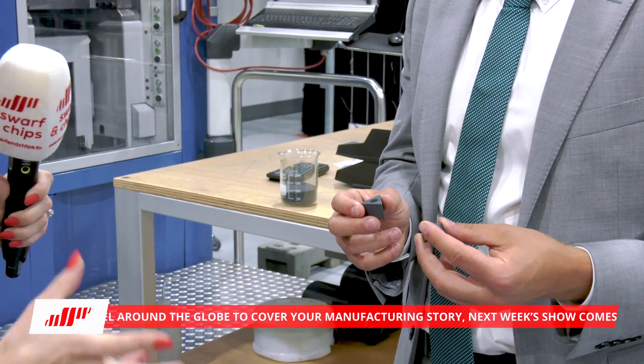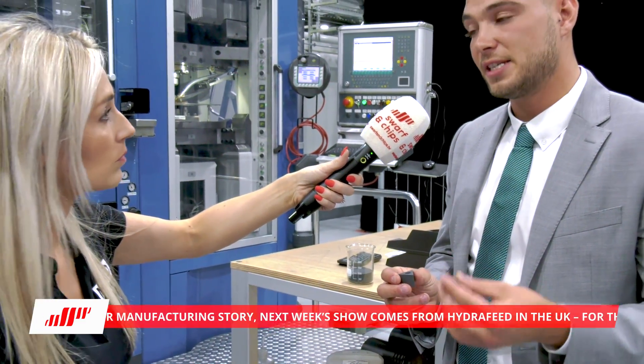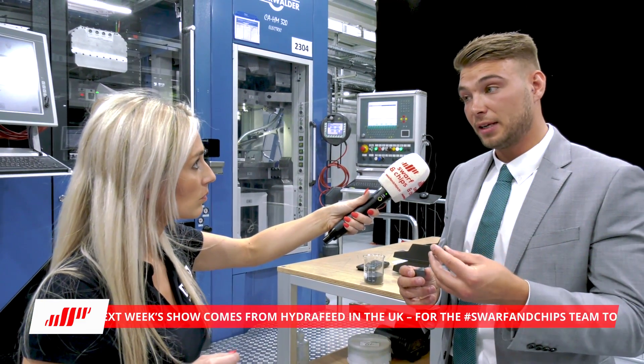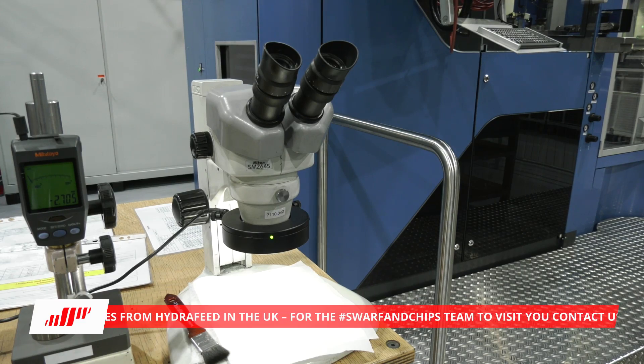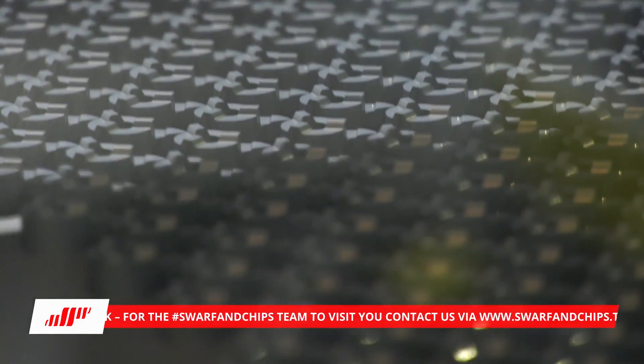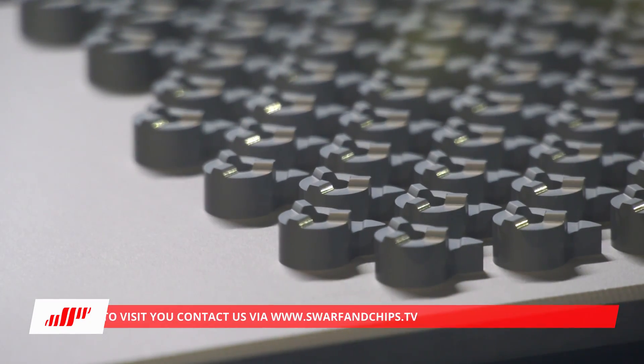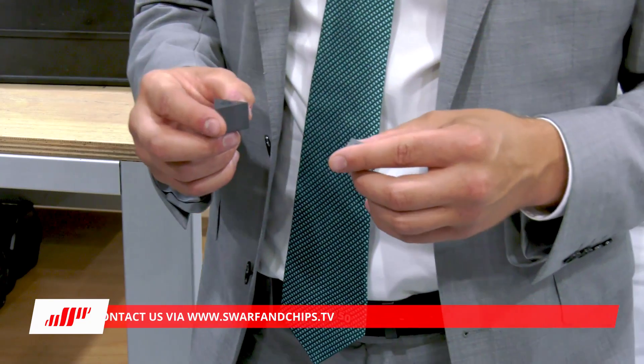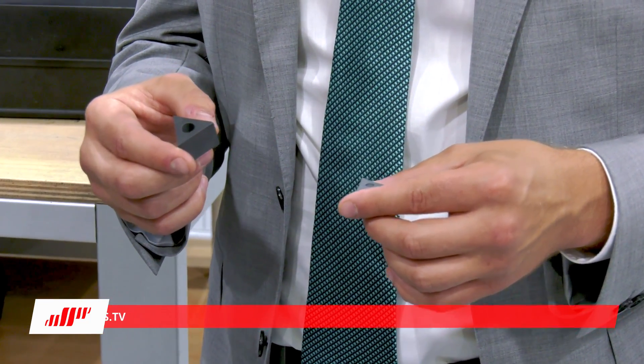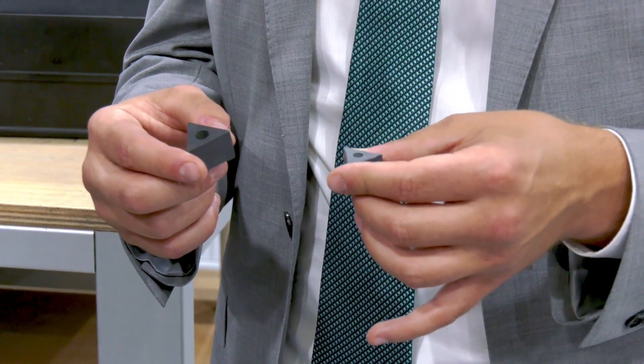So talk us through the sintering process — what is that? There are two steps: pre-sintering and then sintering. It is essentially loading the blanks as they come off the powder press into an oven for around eight hours at about 1,200 degrees. During that time the shrinkage occurs. Does it strengthen the product? It's actually not a necessity that we need it — it's just a process that happens when the material is kept at heat for a long period of time.